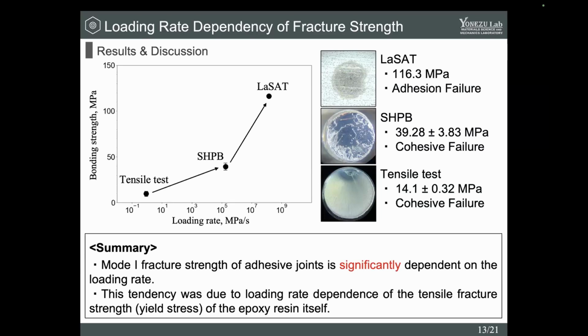It indicates that as the loading rate increases further than the SHPB tests, the strength of epoxy resin itself increases too much and it exceeds the interfacial strength. So therefore, this increasing tendency was due to loading rate dependence of the tensile strength of the epoxy resin itself.